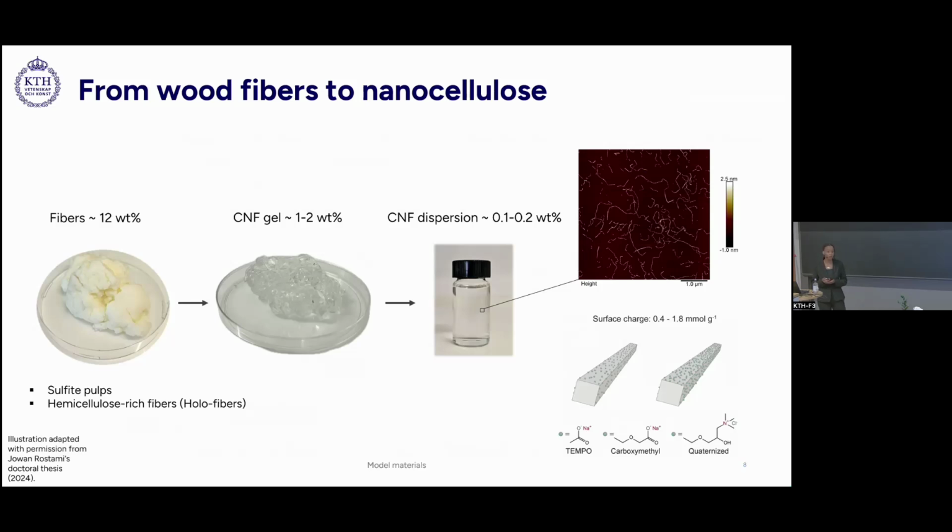And the resulting fibrils had widths of around 2 to 4 nanometers and were over 500 nanometers in length. And here we chose to work with anionically charged carboxylated fibrils by TEMPO oxidation and carboxymethylation, and cationically charged fibrils by quaternization.